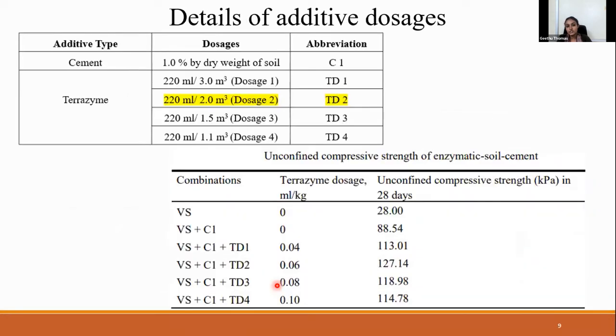The additive dosage used in the present study is 1% cement, in order to reduce the use of traditional additives, and the optimum dosage of Terrazyme is found out from the unconfined compressive strength test as well as the consistency limits test. From the evaluation of the unconfined compressive strength results, we have obtained that Terrazyme dosage 2, that means 220 ml per 2 meter cube of soil, gives the best result. That means almost 4.5 times the unconfined compressive strength of untreated soil is obtained because of the presence of 1% cement and Terrazyme dosage 2.